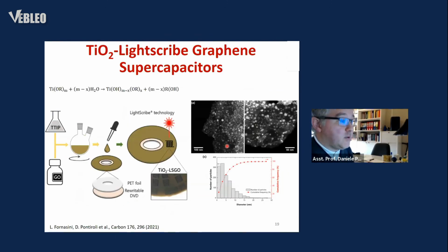And in particular, we managed to produce laser-scribed graphene decorated with titanium dioxide nanoparticles by means of one-pot photothermal conversion of a precursor containing an aqueous solution of both graphite oxide, which is the precursor of graphene, and titanium isopropoxide, which is the precursor of titanium dioxide nanoparticles. And the successful graphene decoration with titanium dioxide nanoparticles, mainly in anatase form, has been confirmed by transmission electron microscopy, as we can see in this picture, but also via Raman spectroscopy, X-ray diffraction, and XPS spectroscopy.